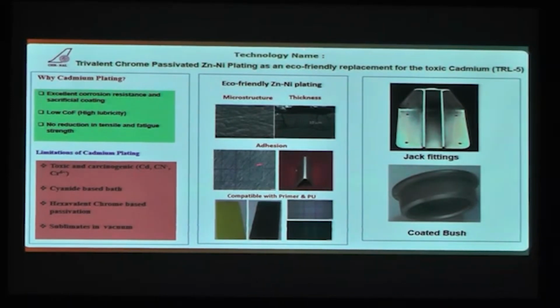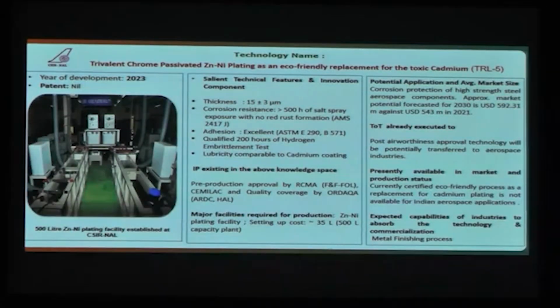It has been evaluated for adhesion through the scratch test and the bend test. You can see that there is no peel off of the coating, and its compatibility with the primer and the PU has been established. And this is the setup we have for the development of the 500 liter facility for production of the zinc-nickel coatings. These are some of the salient features, and the thickness is in the range of 15 to 18 microns.